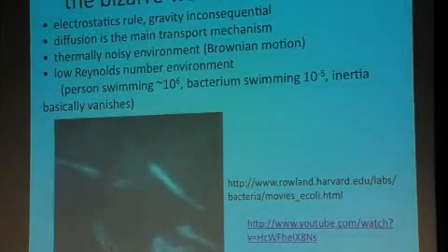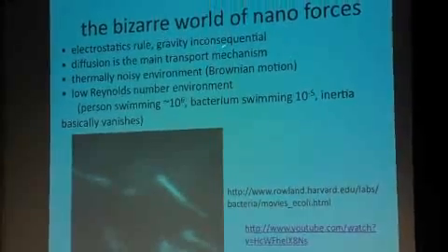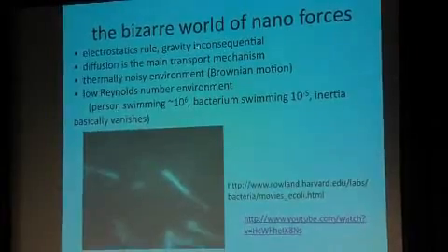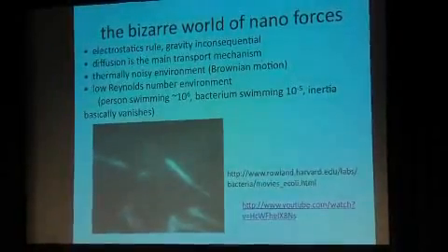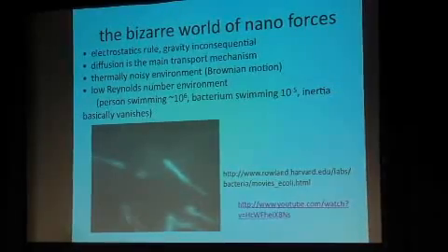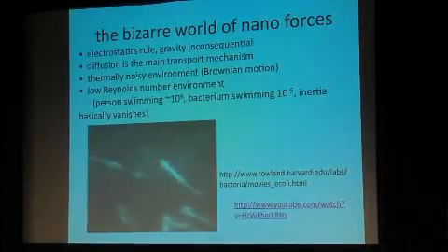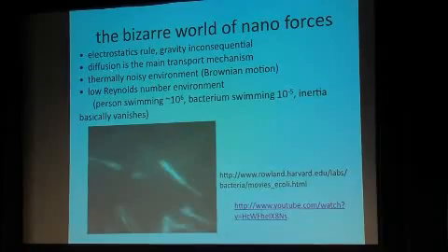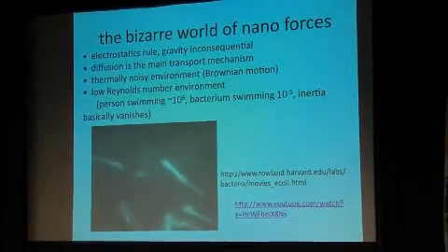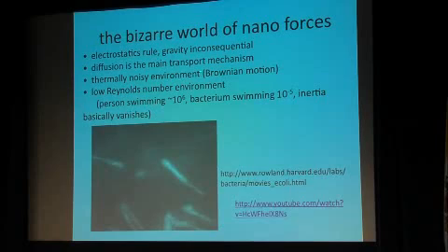Okay, so the main forces and energies that we have to worry about are electrostatic and chemical bonding energies. Okay, so we have kind of a bizarre world at the nanometer scale. Gravity inconsequential for true nanoparticles. Electrostatics, very, very important in terms of determining whether particles stick to each other, whether they stick to a surface. Diffusion and convection are the main transport mechanisms, and we're in a thermally noisy environment.